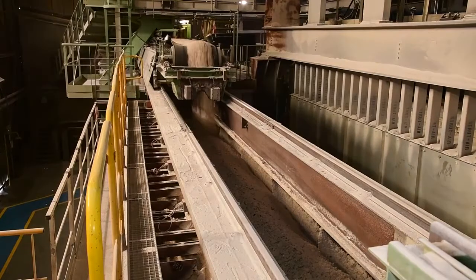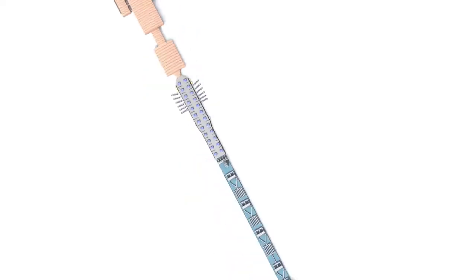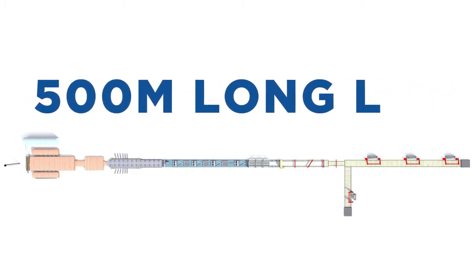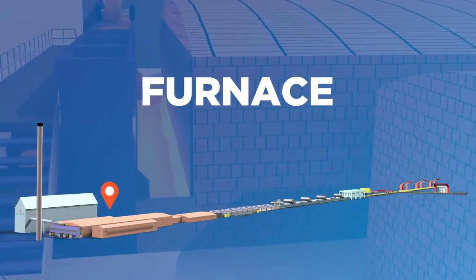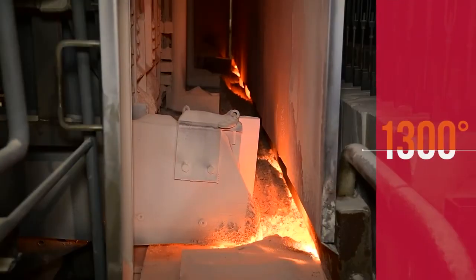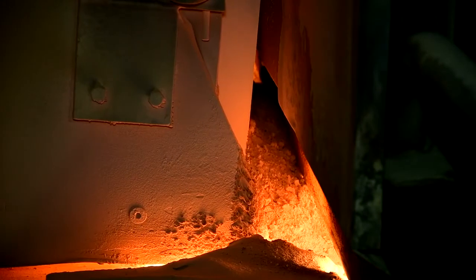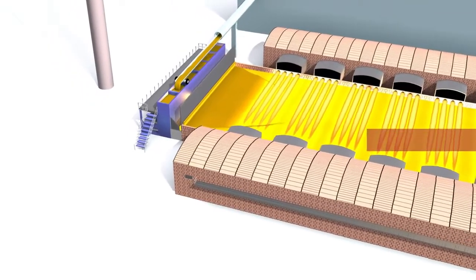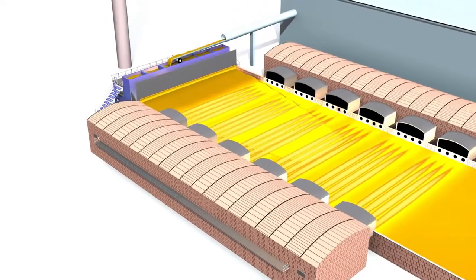About 4 to 5 tons of the batch are conveyed around every 5 minutes to be distributed in the batch charger. During the process, a flat glass ribbon of uniform thickness is formed on a 500-meter long line. The batch charger regularly lays down raw materials at the furnace entrance on a part of the line called the doghouse. The raw materials drop onto the 1,300 degrees Celsius molten glass already contained in that area and are continuously pushed inside. In the melting zone, the batch of mixed raw materials melts at a temperature of 1,550 to 1,600 degrees Celsius until it becomes liquid and merges.